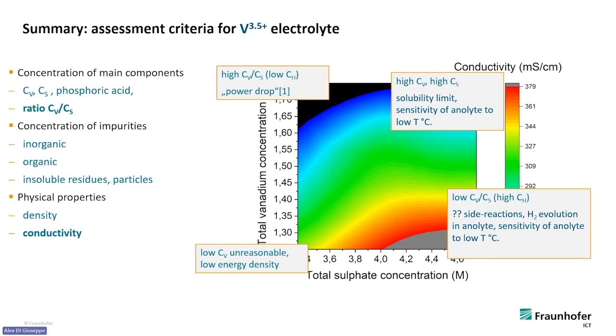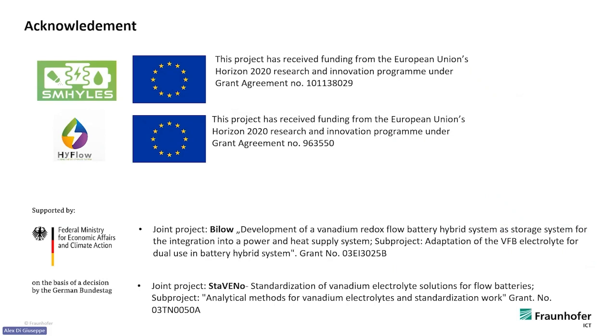So always when we look in this space, you have borders and limitations. If you go too high in acid, you can have side reactions like gassing. If you go too low in acid, you have lower temperature stability. So you have a lot of limitations which you have to take care of when you design such electrolytes. So we have to test it all now. And this is actually the end of my talk. So we finally made an electrolyte which is as good as a regular electrolyte, but has higher thermal stability and that we can use in our Bilow project. So I'm open for any questions.